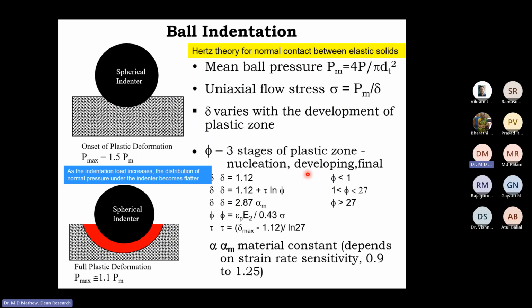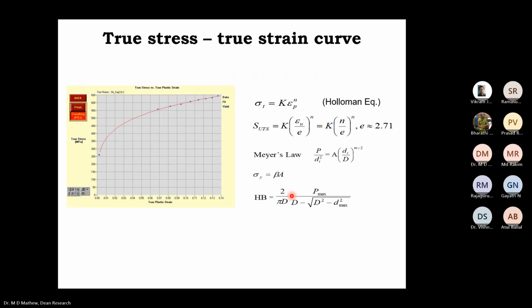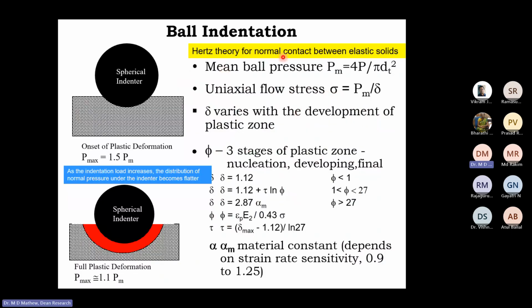Now you need to get the true stress. So how do we get the true stress? So again, we have the load P, which is the load on the indenter. And then you can determine the mean ball pressure using an equation like this, 4P/π dt squared. And once you have the mean pressure, then you can evaluate the flow stress, uniaxial flow stress sigma, using this equation that sigma is equal to the mean ball pressure divided by a parameter delta. And the parameter delta does not have a fixed value. Its value will vary as the plastic zone size under the indenter evolves. So it's a bit of a complicated stuff. I'm not going into that. So the point that you may notice is that we are now able, from the load data, to derive the uniaxial flow stress corresponding to each of the uniaxial flow strain values.